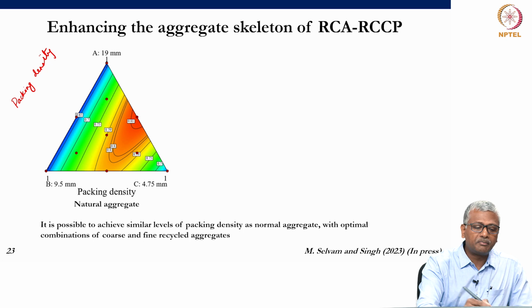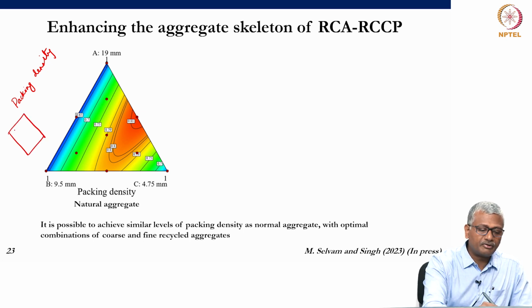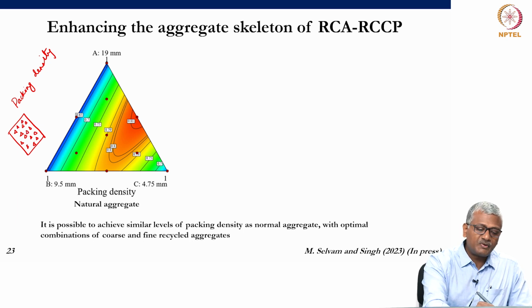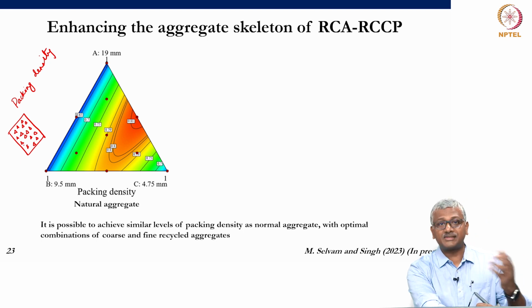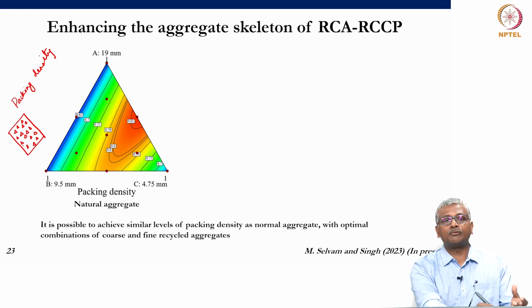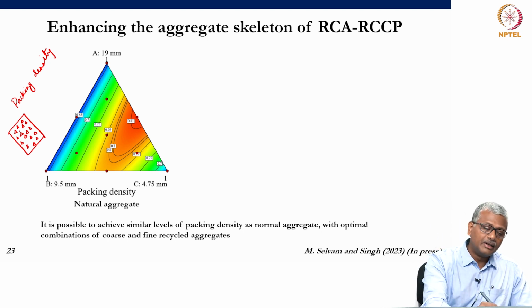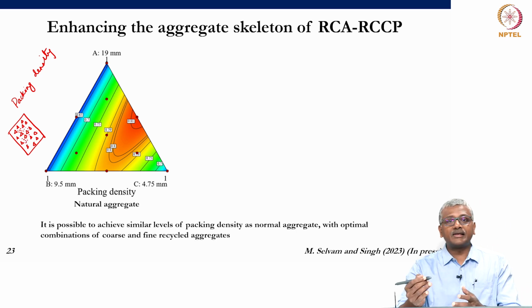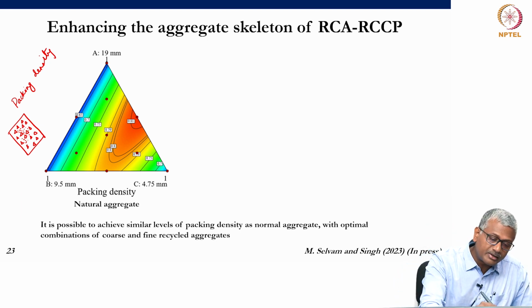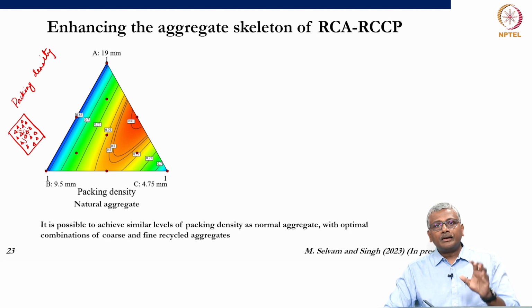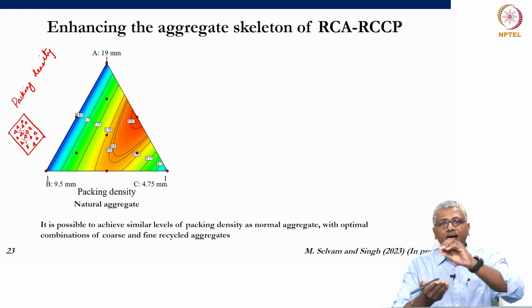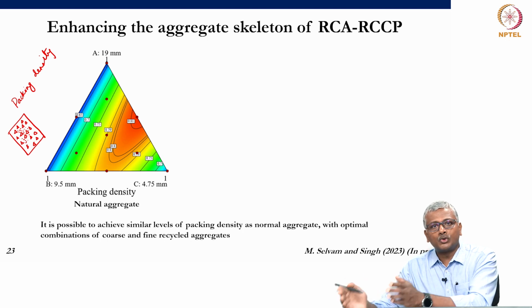Now, what you are simply doing is, let us say you have a container, you are filling the container with coarse particles first, right. And then you know that there are voids and gaps between these coarse particles which you have to identify properly in terms of understanding what is the voids that will remain after efficient packing of this size particle. And those voids you start filling up with smaller particles, and then you recognize the voids in that mixture and fill it up with even smaller particles and so on. So, essentially what you are trying to do is adjusting your sizes in such a way that the voids left behind by one size are nicely filled up by particles of the smaller size, and so on ad infinitum, right.